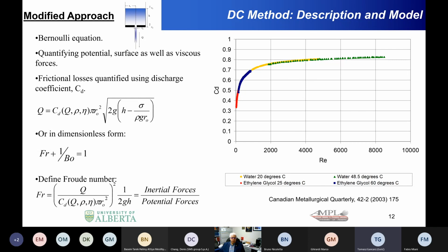And so these three parameters of viscosity, surface tension, and density are three unknowns for a material with unknown properties, and you've got 100 data points to try to fit and find the best values of these three properties that agree with the flow conditions obtained in the experiment.